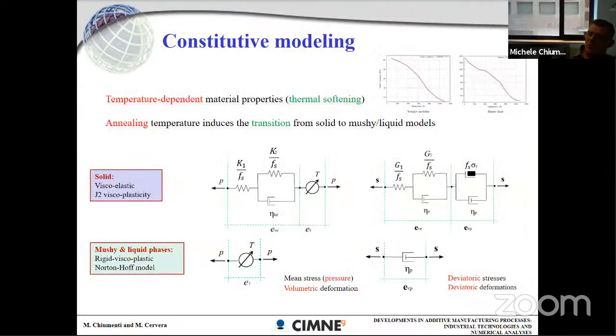Next observation, constitutive modeling. We are working on a more accurate constitutive model at the moment, but just to clarify a bit, all the material properties are temperature dependent. This is a key point, and particularly it's important to consider the yield stress as a thermal dependent parameter. Something that was, at least for me, new, if I can say, is that our model behaves differently when the material can be assumed as solid and when the material is assumed as mushy or liquid.